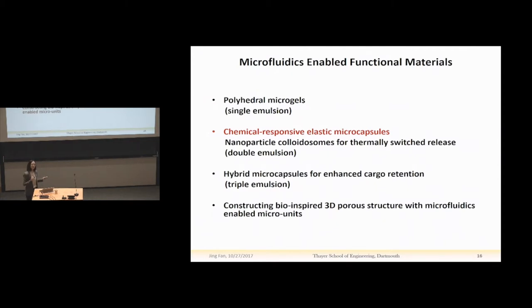So how to improve the efficiency of the surfactant we use? We propose to develop some smart capsules which can deliver the surfactant to the oil-water interface, and release their cargo in the vicinity of the interface only. This will induce a high local concentration of surfactant near the interface. Okay? But how to do this?